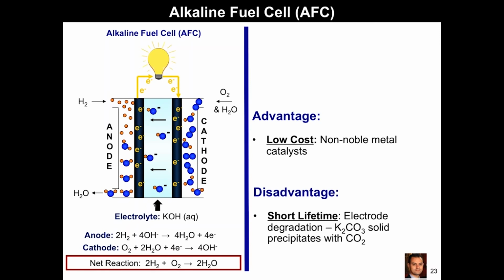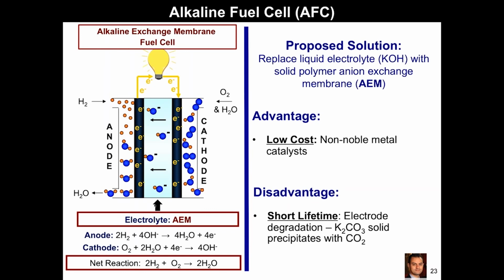And the downside is when you use liquids that have mobile cations and anions, such as potassium hydroxide, and you have any carbon dioxide in the fuel, typically you'll form potassium carbonate precipitates. And so the lifetime of the fuel cell is very short. And so this is why this has not been commercialized. But within the last decade, it's been proposed that if we had a single ion conductor, particularly a polymer membrane, like an anion exchange membrane, we can circumvent this problem. And so there's been sort of a search for chemistries and materials that could solve this problem in this field.